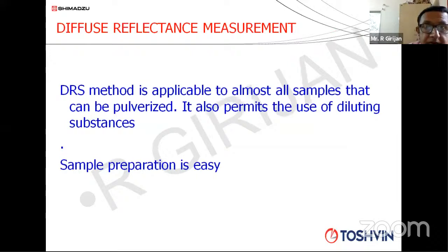We are coming to the diffuse reflectance measurement, what is normally known as DRIFT analysis. The DRS method is applicable to almost all samples, especially powder samples that can be pulverized. Pulverized means you will have to mix it with potassium bromide. You should be able to grind it in a small mortar and pestle. We triturate the sample with potassium bromide. Once you mix it, you can take the sample mixture, that is, sample plus potassium bromide, directly in the DRS attachment. And what is the proportion? You take about 2 milligrams of powder sample and about 100 milligrams of pure, dry, spectroscopy-grade potassium bromide, mix it well and take it.